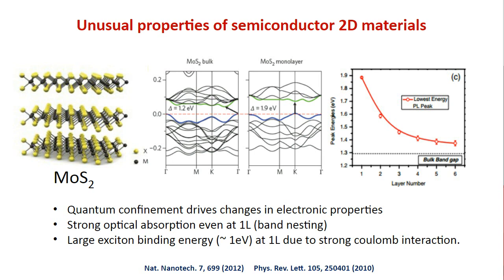Now we know that the direct band gap systems are preferred for application as they absorb light very efficiently. Indirect band gap systems are weak absorbers. Therefore, the take-home message is that a single layer MoS2 is a very, very strong photodetector compared to the bulk, even though it is only a single layer, right?